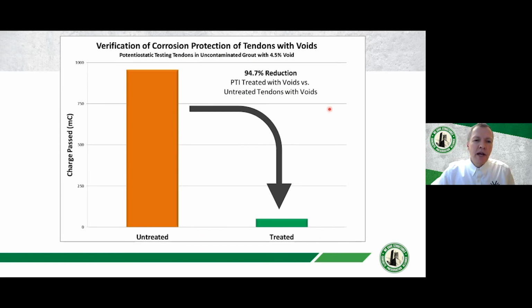Similarly, you can do the same type of testing, potentiostatic testing, but instead of samples with chlorides here, they're tendons with voids, 4.5% voids in this case, and you can see that there's a big reduction from untreated to treated samples in the amount of current or charge that's passed, which basically means you have a lot longer time frame to failure with the treated tendons.